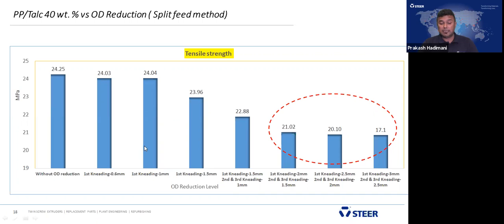Next, again in the first kneading section, we reduce 0.5 millimeter per side, so 1 millimeter on both sides, and no difference. We didn't find any difference in the mechanical property. Up to here in the first section of the kneading, at 1.5, there is a slight reduction, but it's negligible. We didn't observe a change because that shows the polymer. It's very important when you feed